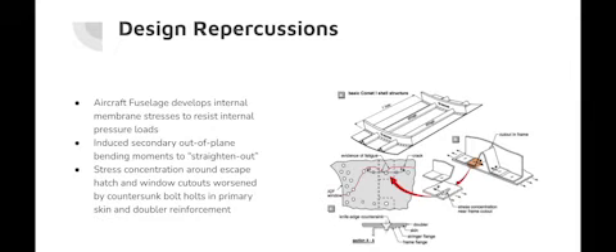their thickness to attempt to resist the internal pressure loads. Due to the curved shape of the fuselage, these forces induced secondary out-of-plane bending moments to straighten out the curvature. In addition, the stress concentration around the escape hatch and window cutouts was exacerbated by countersunk bolt holes, creating a knife edge in both the primary skin and doubler reinforcement. The cracks that grew in a bay from one cutout to the next were not tolerable and resulted in the ultimate failure of the structure.